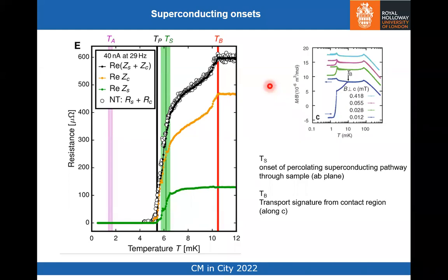Okay, so now what about superconducting onset then? We're still in zero magnetic field. So orange, let's look at green first. Green is the sample, the real part of the sample impedance. That shows a clear superconducting transition at 6 millikelvin. And as we're measuring resistance with nano-ohm resolutions, I haven't shown this on a logarithmic scale, but the resistance in this regime is at the nano-ohm level. So it's truly a superconductor. So that defines a transition temperature, which I'm going to call T sub S. That's the transition temperature in the sample.